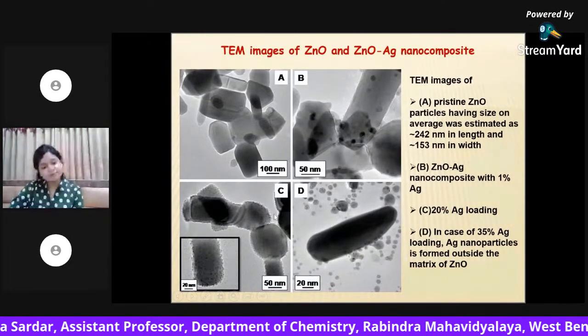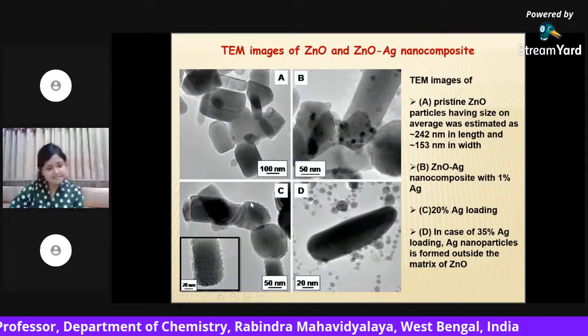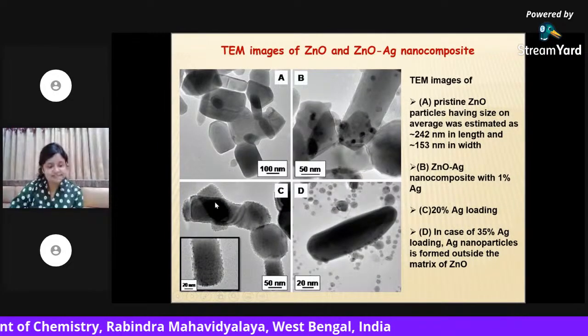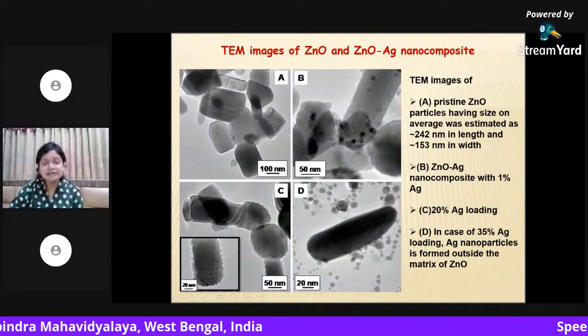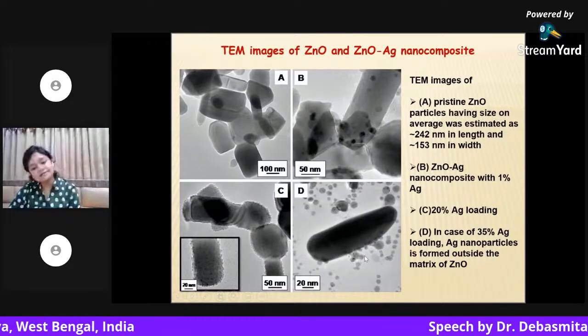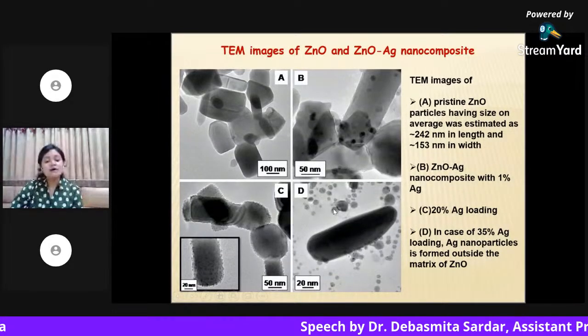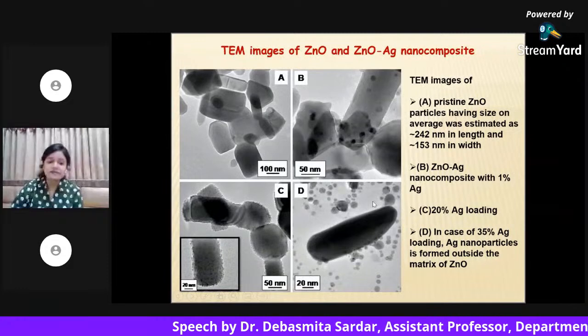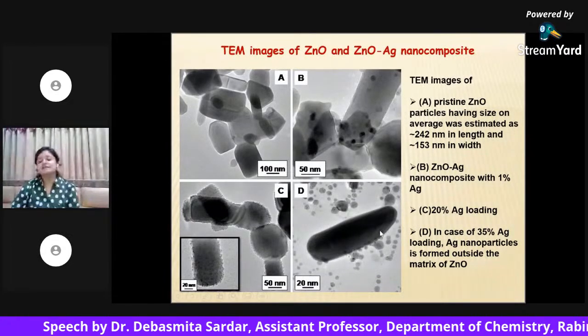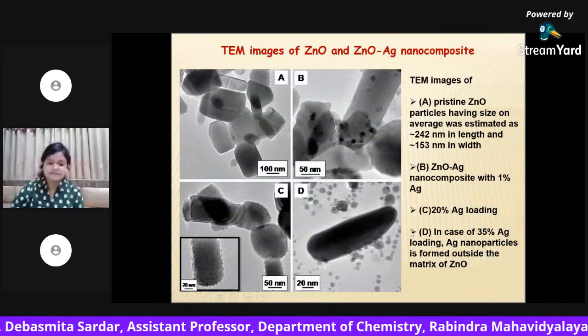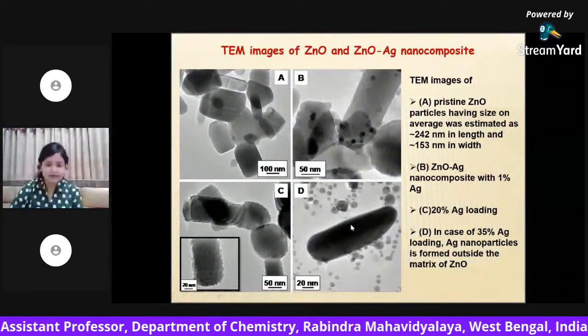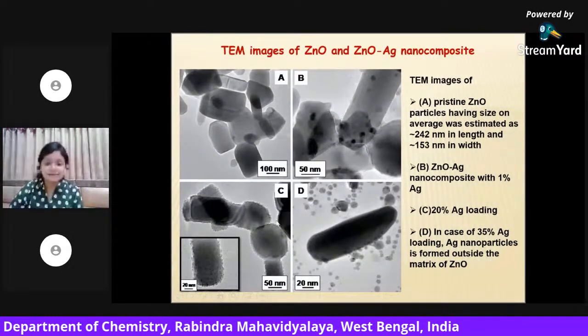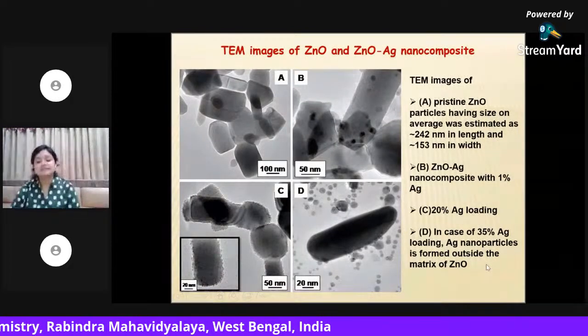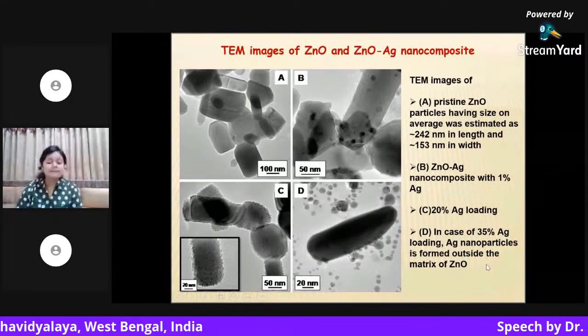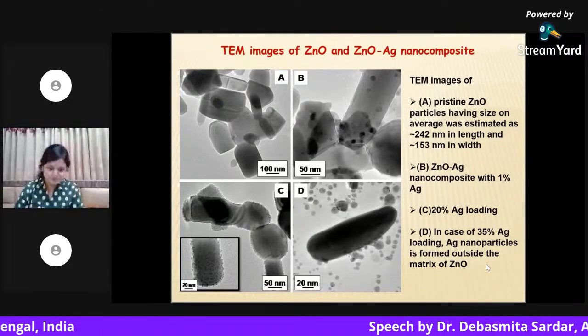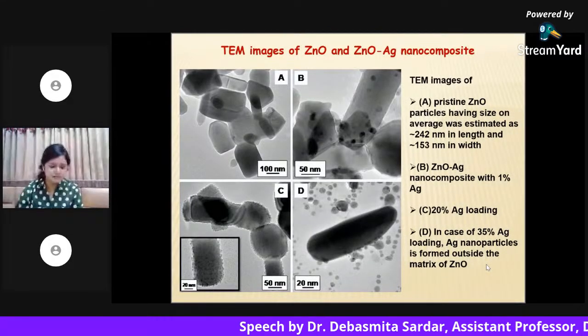Lots of silver nanoparticles have been seated on the zinc oxide matrix. But after increasing the percentage beyond 35%, we can see that the silver nanoparticles can no longer be seated in the ZnO matrix. They are scattering outside the matrix in the solution. So 35% is the optimum. We can say that 35% is the optimum amount of nanoparticles which can be seated on the ZnO matrix.